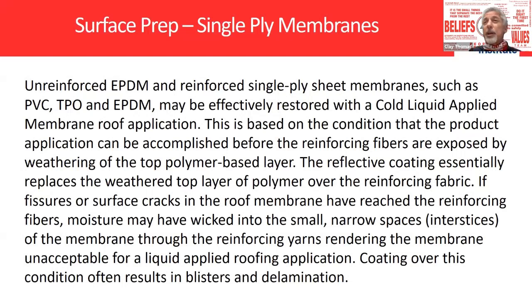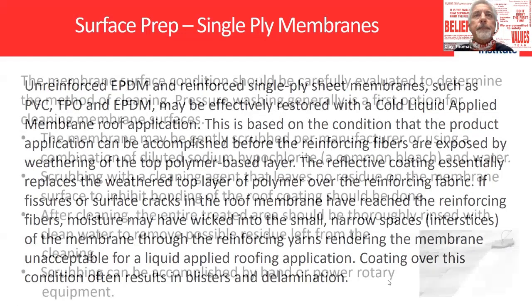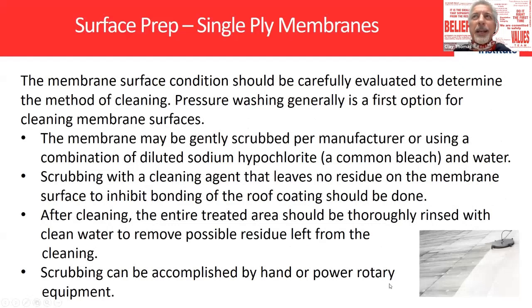One of the things I did when I put the coatings on, and I did some of the samples like you guys at home, I did them on my own roof. We were in the middle of the pandemic. I did temperature tests, and I had just put down a white modified, and I put white coating right next to it, and the white coating was 25 degrees cooler than the white modified. So amazing what reduction in temperature you can get on the surface with a reflective coating with the high SRI. Lonnie, remember in the day we used to think aluminum coating was the thing. Aluminum coating has an SRI of 60. White is over 100.